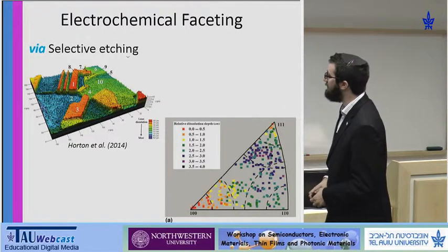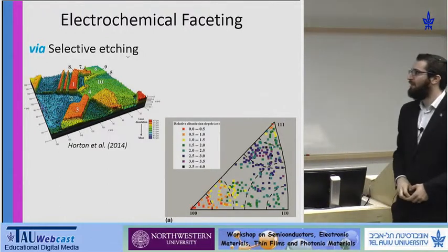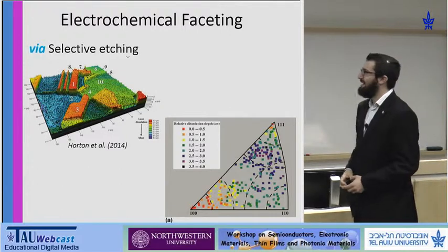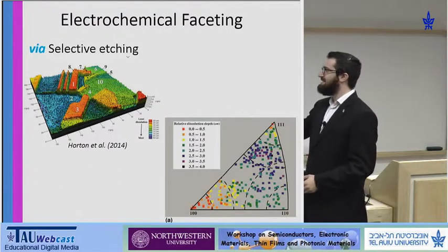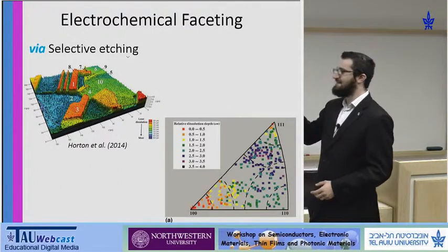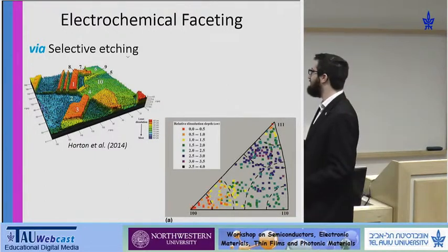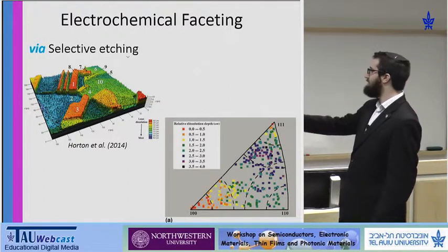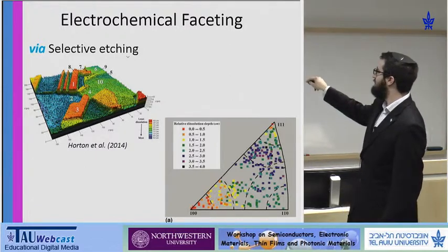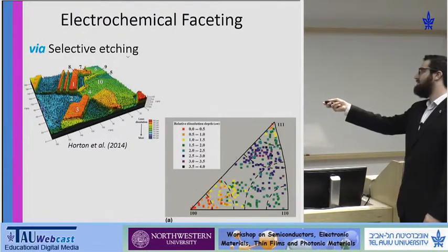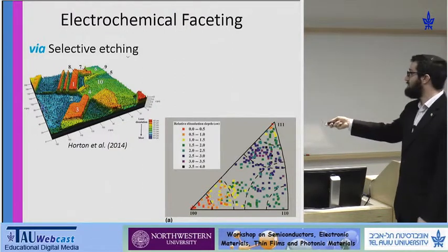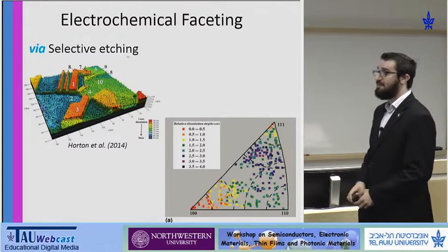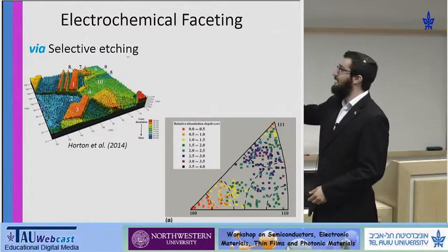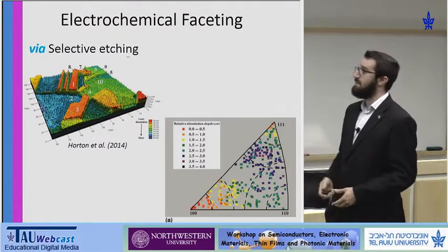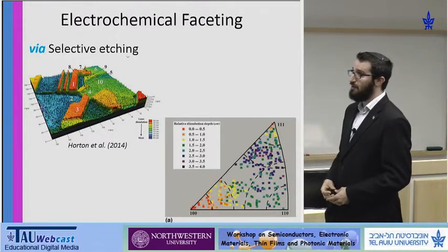On the left, we see work done a few months ago by Horton, where he looks at EBSD as a way of seeing which grains are selectively etched to make these faceted surfaces. And we see very slow etch rates on the corners of the stereographic triangle. And when you get to about 20 to 40 degrees from either 111, 100, or 110, we see a much faster etching rate. And this is a way of modifying the surface to expose different crystallographic planes